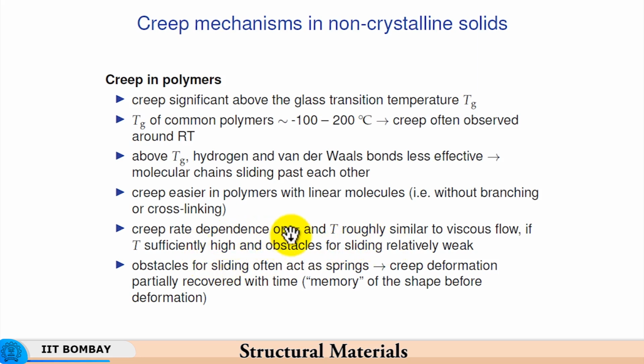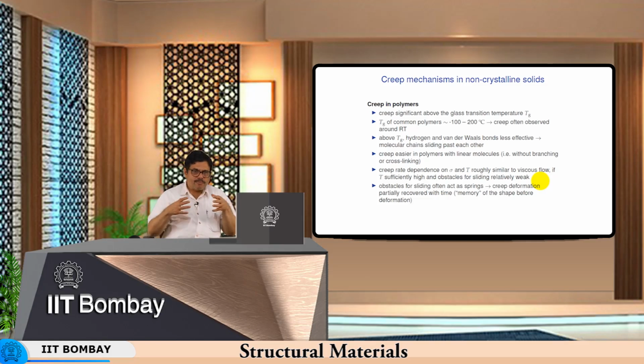So, creep rate dependence on sigma and T is roughly similar to viscous flow. If T is sufficiently high and obstacles for sliding are relatively weak, then the material, the polymer for example, will behave more like a viscous liquid. So, normally when we do molding, let us say polyvinyl chloride, PVC is known to be a viscous polymer. When you heat it, the polymeric chains are able to slide very efficiently with respect to each other, and therefore, the polymer flows as a viscous liquid. So, the viscosity of the liquid is very high.